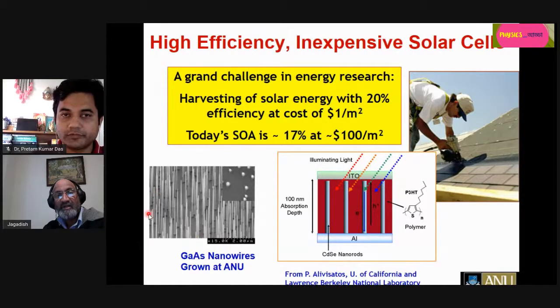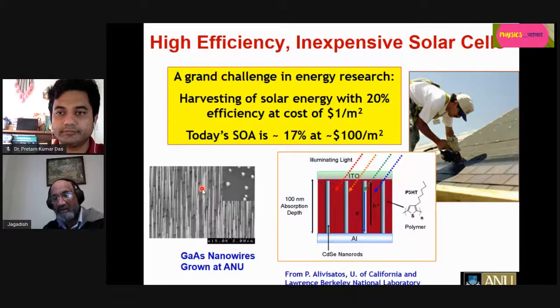And the key challenge is how do we reduce the cost of the solar panels, say, from $100 per square meter at a 17% efficiency to $1 per square meter with a 20% efficiency or so. That means even the packaging material may cost you more than $1 or so. So that's where scalability and manufacturability become important. Instead of using cadmium selenide nanorods, which Professor Alivisatos' group has been using, we start using gallium arsenide nanowires, because our expertise is in III-V semiconductors, and we just want to see how we can contribute to this particular field.